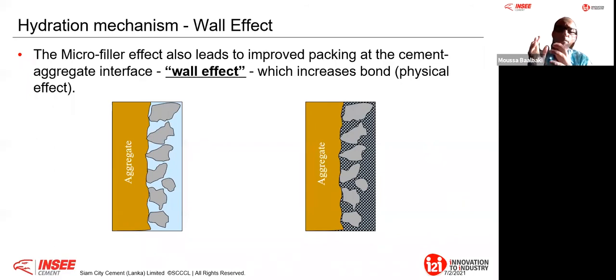And at the same time, I will show it later in the slide, when we move from normal concrete to high performance concrete, we have what we call the transition zone. The quality of the glue of the cement hydrated product with the coarse aggregate is also very important. This is what we call the wall effect. How can I increase the bond in the wall effect? Because if you take normal concrete and break a cube, you will not break the coarse aggregate. It goes through the cement hydrated paste.